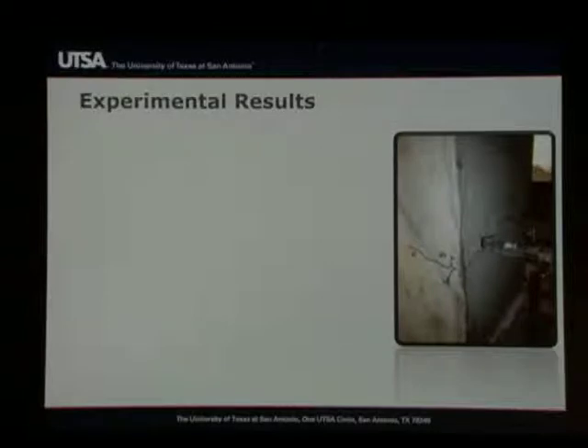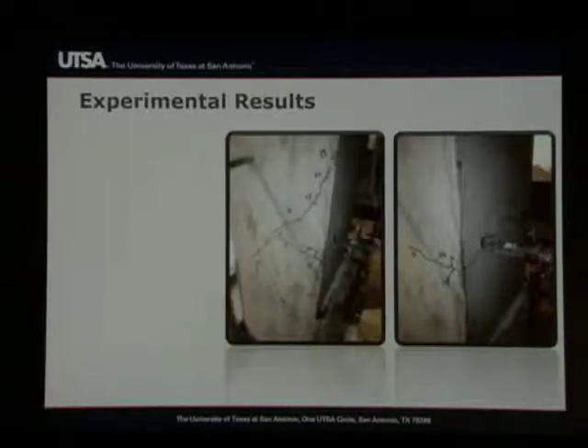This is the same progression, but in actual images from tests. So you see how the cracking starts right at the location of the bar. We really can't see what's going on at the surface of the bar, but those cracks, these are the flexural cracks. From my strut and tie model, you will recollect that this area was expected to be in tension. And so from those flexural cracks, you see those cracks start to propagate towards the back of the hook.